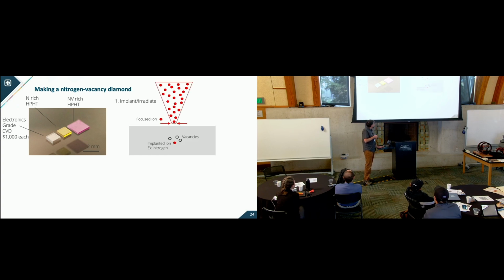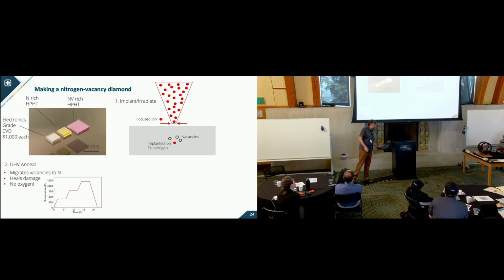So these are the starting materials, but this is really the usual starting one. For example, here's our focused ion beam. We can focus this down to 50 nanometers, and you make defects and vacancies. Now that's not actually the end. You have to high pressure, or ultra high vacuum, anneal these diamonds. That migrates the vacancies to nitrogen and heals some damage, but you really have to watch out for any oxygen, which is why it's ultra high vacuum, because diamond will just turn into carbon dioxide if you anneal it in air above 400. So you've got to be a little careful with that one.